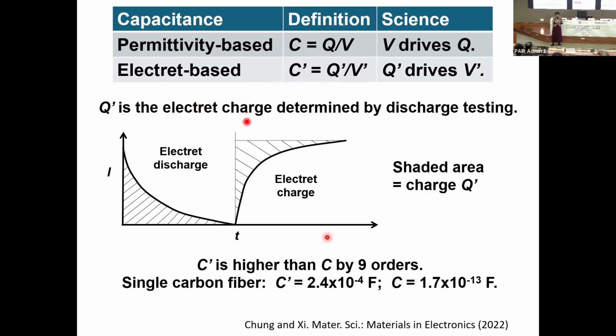is the electret charge as determined by discharge testing. That is current versus time. You integrate the area under the curve. That gives you the charge. And that is the Q prime, the electret charge. And V prime is the electret voltage. And so C prime is the electret-based capacitance, with Q prime driving V prime. And it turns out that the C prime is higher than C by, say, 9 orders of magnitude. It's just a different quantity.